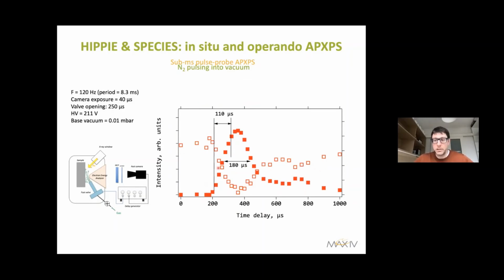In that particular case, the duration of this gas pulse was 180 microseconds, but another way of claiming the time resolution is the rising edge of 110 microseconds in this particular case. I think this is the more important time, because that gives the difference in the chemical composition, in the chemical potential, and this difference can be huge. It can be several orders of magnitude. The idea here is to correlate the composition of the gas phase to the surface.